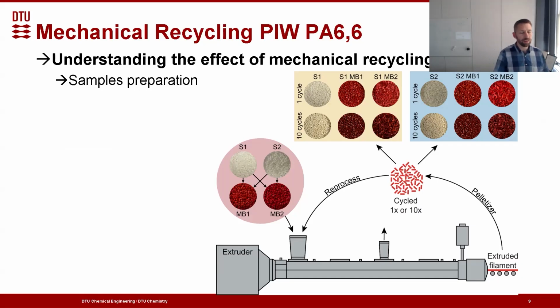And as you can see here, there's a clear coloration happening through these recycling steps, even though it's only 10 cycles. It's very clear that the natural grade after 1 cycle compared to after 10 cycles does not look the same. This becomes even more pronounced when we look at the red dye, where we can see a very clear discoloration happening in the system.